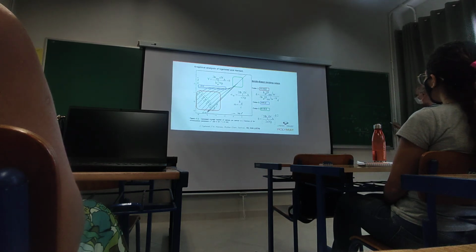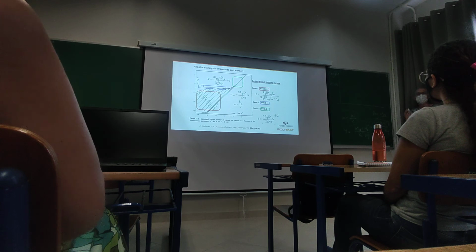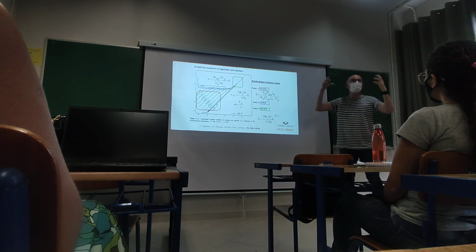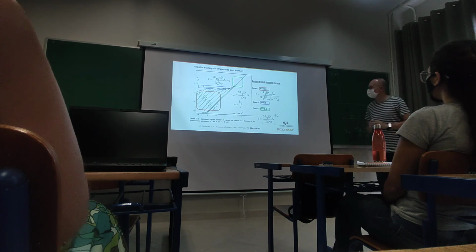Okay? And this occurs when you have, no matter which n, high values of alpha, which means high generation of radicals, or low termination of radicals in the polymer particle, or a small number of polymer particles. Okay? This has to be large, or this has to be small. So this occurs in situations where alpha is high. Okay? High concentration of radicals, or low number of particles, or very low termination of radicals in the polymer particles, to have plenty of radicals in the polymer particles, and the situation will be like in a suspension polymerization. Okay? But with smaller particles.